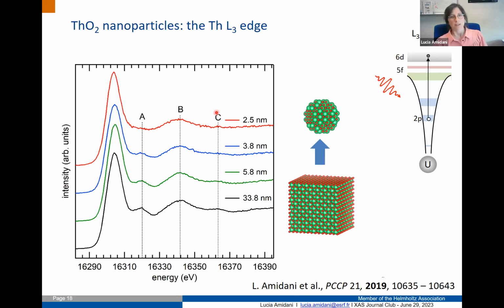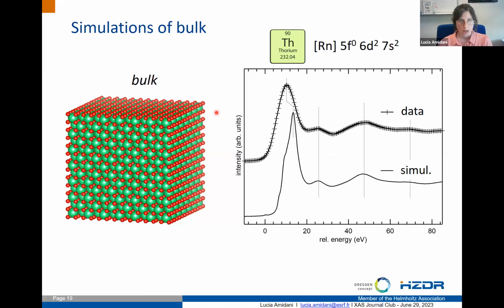We see that in the post-edge features, which are 3: A, B, C, A has disappeared and C is also much lower. So actually this is a tiny effect. It's not a huge change in the spectrum, but we decided we really wanted to investigate if this can tell us something, so of course we decided to do it with calculations.